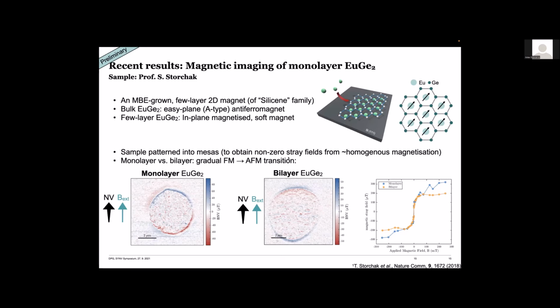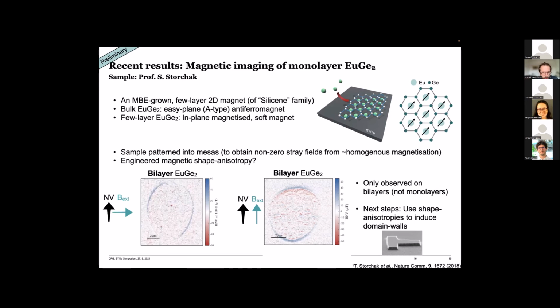Another thing we're doing is we're trying to see to what extent by changing these mesas, so changing the geometry of these magnetic layers, we can possibly engineer the spin textures that are stable in this material. So one thing that we've recently seen, and this is again very preliminary, are first indications of possibly introducing shape anisotropy in this patterning. And here's what I mean by that.